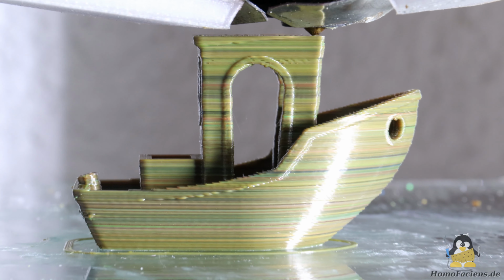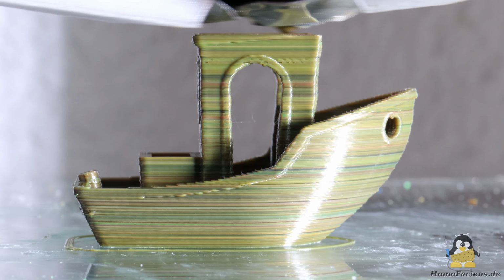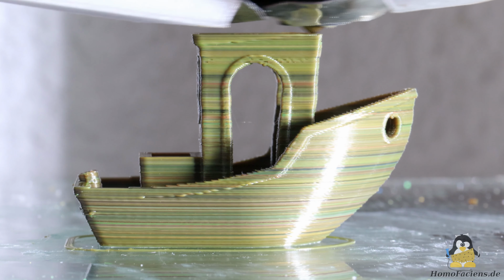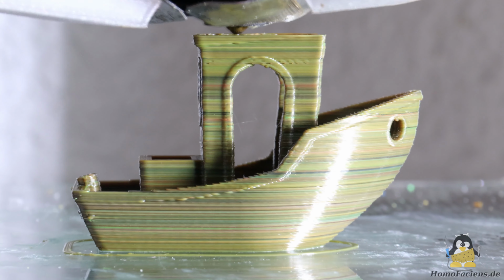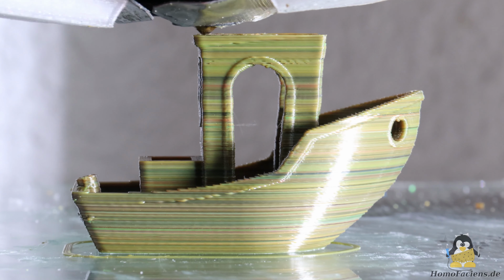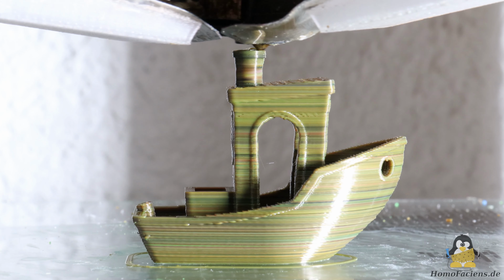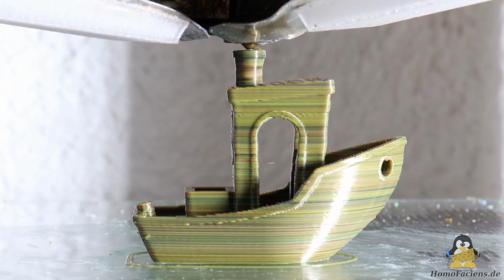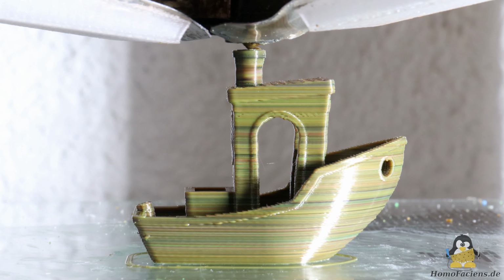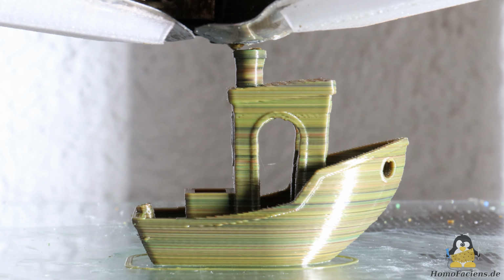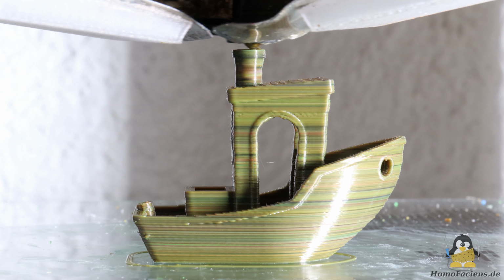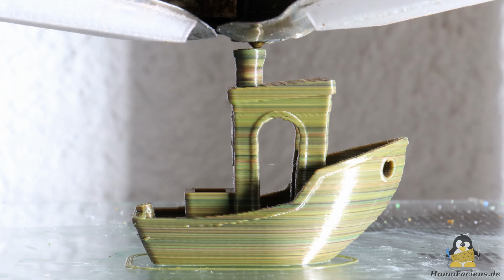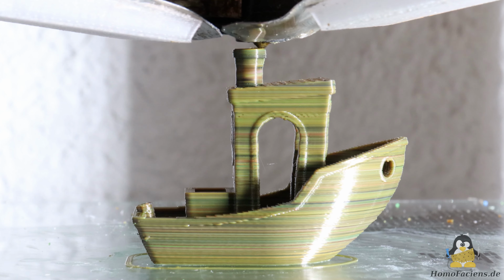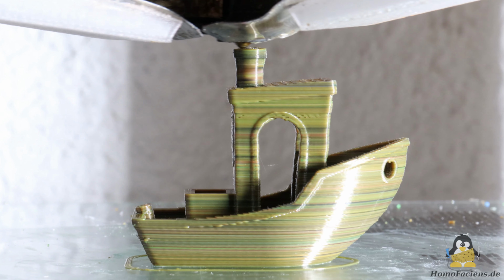Pressure advance is disabled for this print, but it would certainly be needed to be implemented differently than on filament printers. The chimney shows that the extrusion rate is proportionally higher at low speeds than at fast speeds. This structure is obviously printed with over-extrusion. There's still a lot of experimenting and fine-tuning needed to optimize the print results.